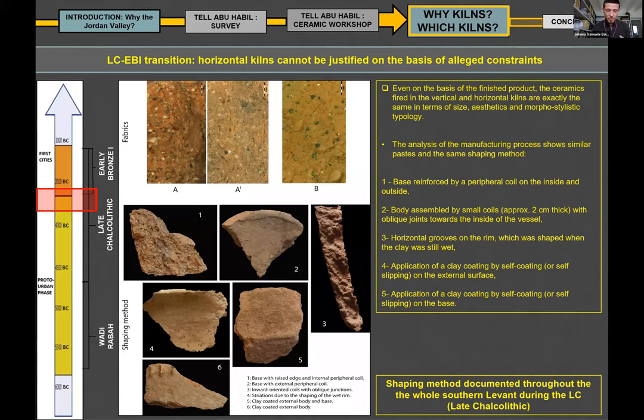Furthermore, this shaping method, this operational sequence, is not surprising in itself. Indeed, it has been recently recognized by Dr. Valentin Roux throughout the Southern Levant during the Chalcolithic, and it is typical of the entire Ghassulian cultural area. In other terms, this operational sequence, this shaping method, corresponds to the technique typical of the people living in the Jordan Valley and in a large part of the Southern Levant during the Chalcolithic. It was their very distinctive way of producing ceramics. So it's not surprising to observe that this same technique and the same people underlying this technique persist at the very beginning of the Early Bronze Age I.